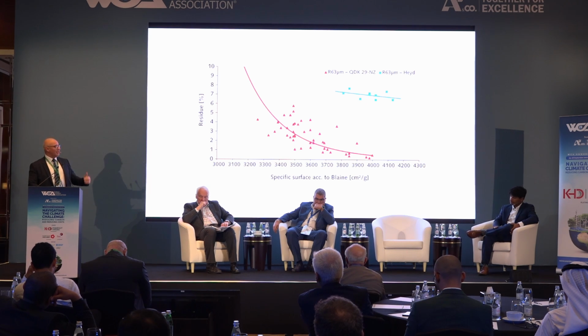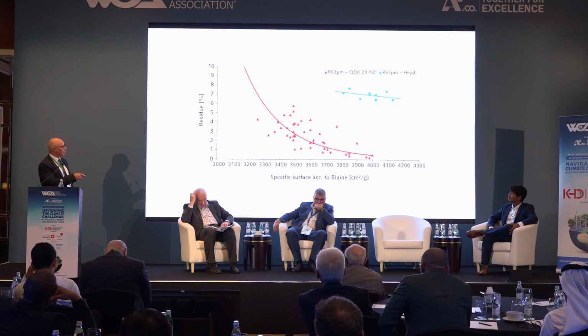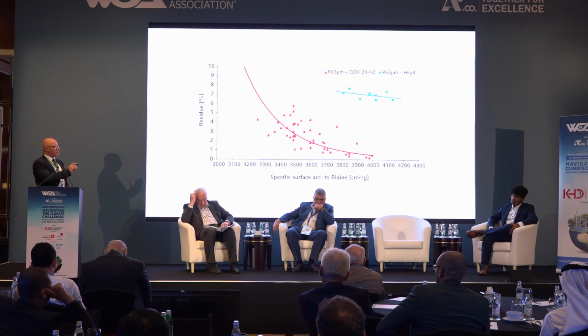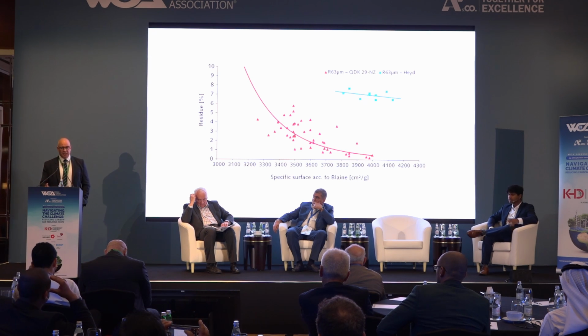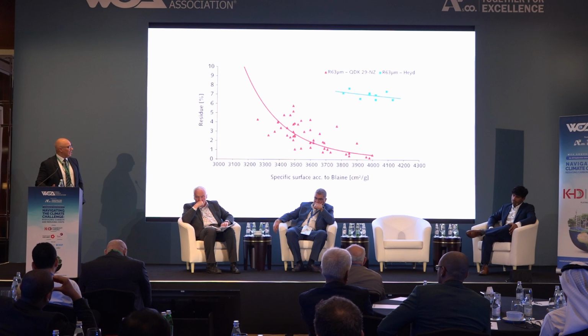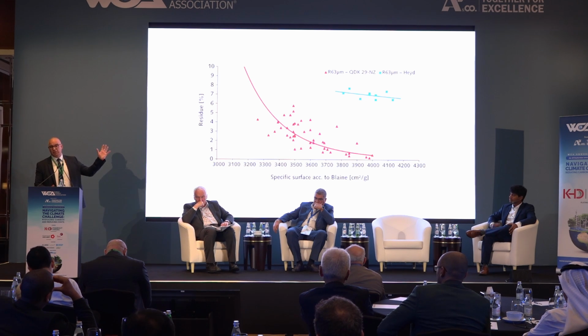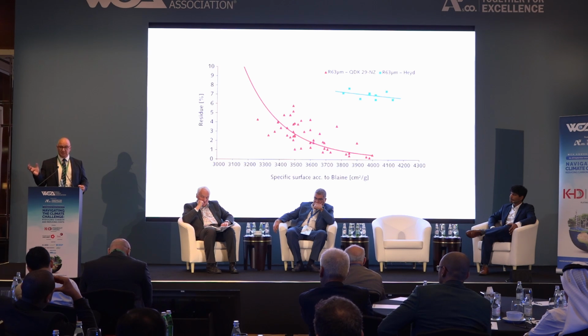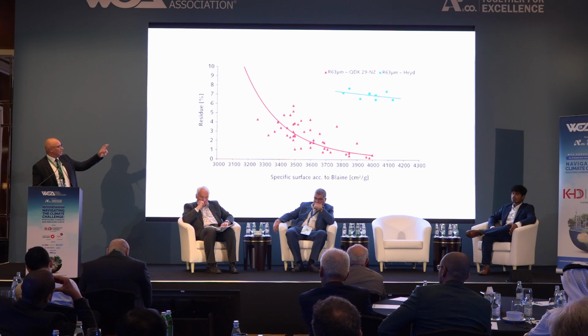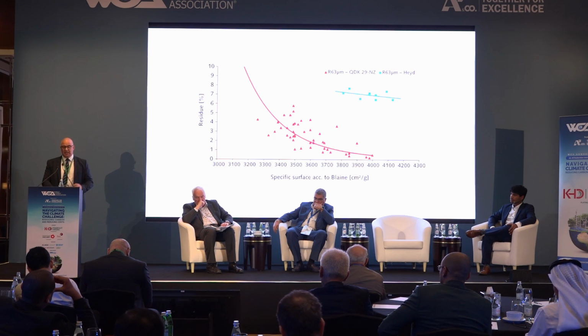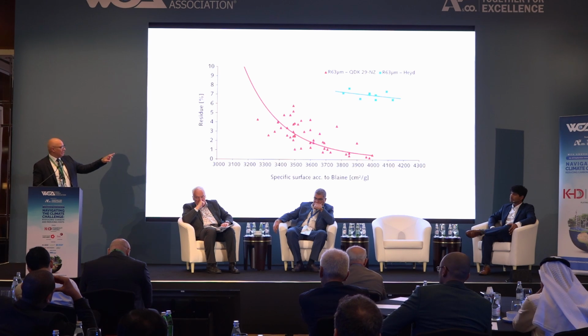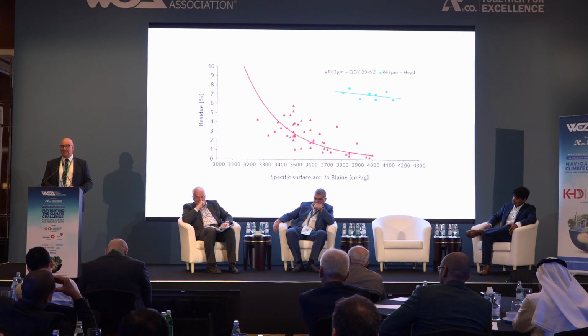This is a case study of this separator. We were changing, I don't know if I have a laser, no, okay. So as you can see in the top right, it was the product that they were producing when they were with the first generation separator. You see that they were working mainly on Blaine. This was a measurement that they were using, less and less used in the market due to the cementitious materials that we are using, and it's giving us a high surface, so the Blaine is a little bit fake sometimes. So here you can see that we have a 4,000, 4,100 Blaine, but the residue, in this case 63 microns, is 6.5 to 8%. They are changing the separator and keeping the Blaine. What is happening is that automatically the residue is going really down and the cement strength is going up.